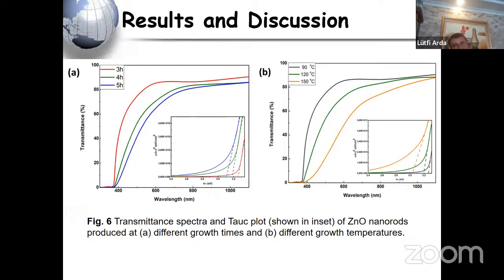thus, the decrease in transmission may be related to the higher zinc oxide nanorod volume, the higher number of defects, and the increase in film thickness, which is consistent with early literature reports. Besides, it has been shown both theoretically and experimentally that the surface roughness has a significant effect on the optical transmittance of thin films. Thus, it can be said that multiple random optical scattering on the rough surface may result in lower transmittance in zinc oxide nanorods. The increment in both thickness and roughness of zinc oxide nanorods with increasing temperature and growth time was reported in our previous study.